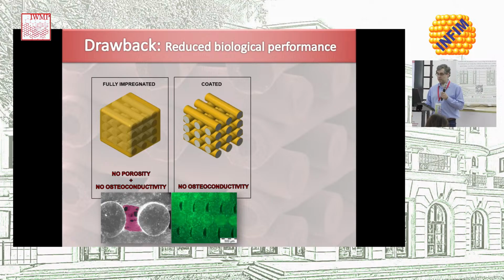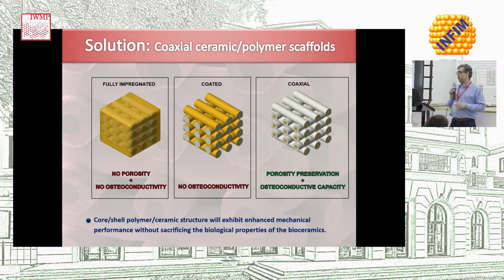And we thought, maybe we can still have the polymer, so we have a composite, but keeping the polymer far from the surface of the ceramic material. So we started trying to produce structures like these ones, in which we have the biopolymer inside the struts rather than on the outside. These coaxial structures will still show an improvement in toughness, that's what we expected, and will preserve both the porosity and the osteoconductive capacity of the material. So how do we produce those types of structures?